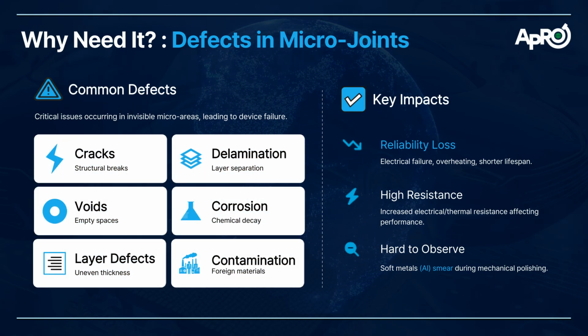Microjoints can develop various defects, including cracks, delamination, voids, and corrosion. These defects cause reliability loss and performance degradation. Especially for soft metals like aluminum, mechanical polishing causes smearing, but ion beam technology solves this issue. Let me explain the polishing stage first.